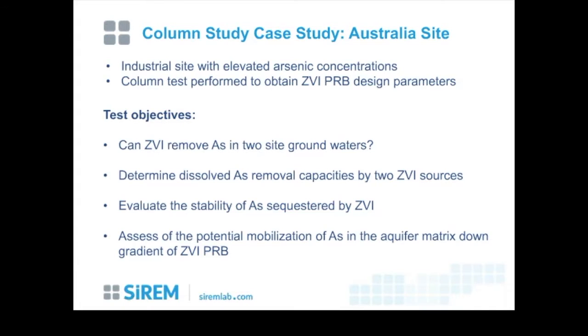So I want to just do a case study for a site, materials that we got from a site in Australia. This is an industrial site that had elevated arsenic conditions, and they were looking at understanding ZVI PRB design. They were very concerned about arsenic mobilization, so they had a variety of different test objectives. Initially they asked, are we going to get treatment of the arsenic in 2 different site groundwaters? So they provided 2 different groundwaters. They also wanted to evaluate 2 different iron sources to see if either one had a better removal capacity, as well as look at the stability of arsenic sequestered by zero-valent iron. So the arsenic was sequestered into zero-valent iron, and would it stably stay there, or would there be conditions under which it would be released?